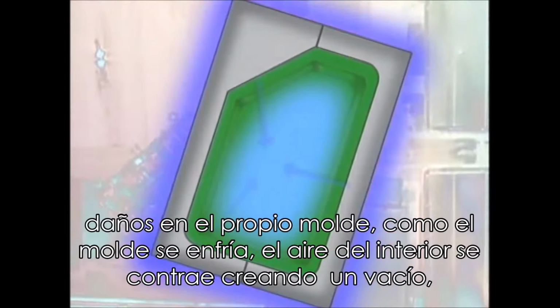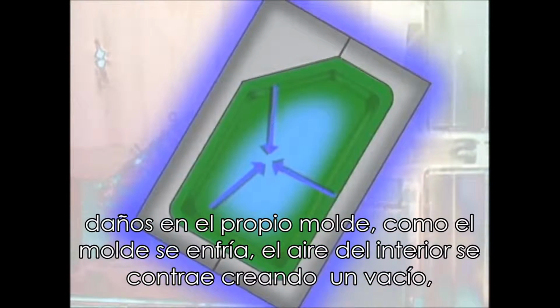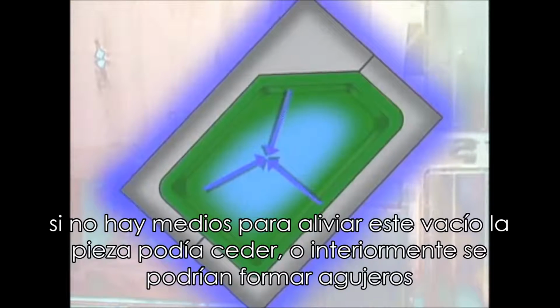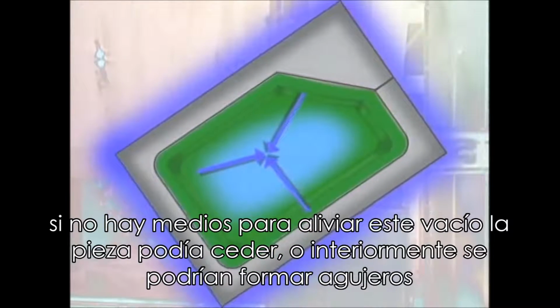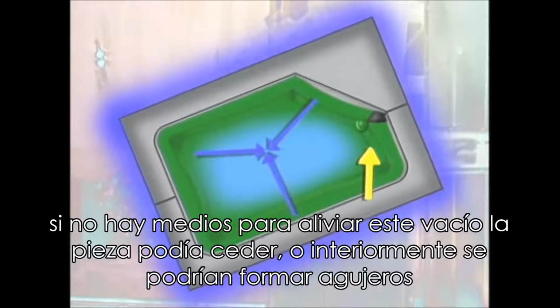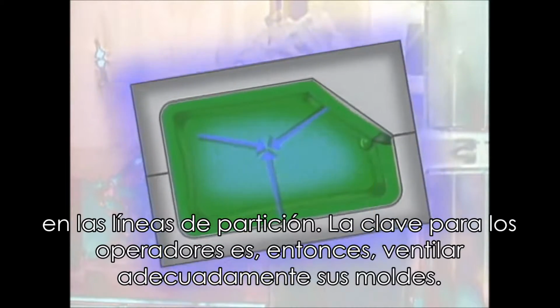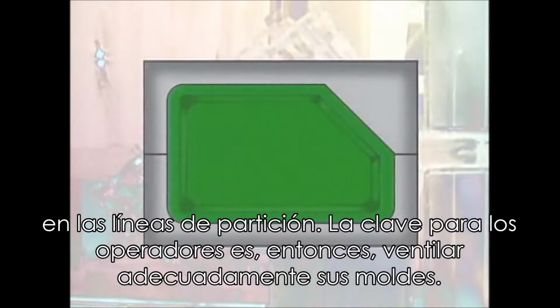As the mold cools, the air inside contracts, creating a vacuum. If there is no means to relieve this vacuum, the part could cave in, or inward blowholes could form at the parting lines. The key for operators, then, is to properly vent their molds.